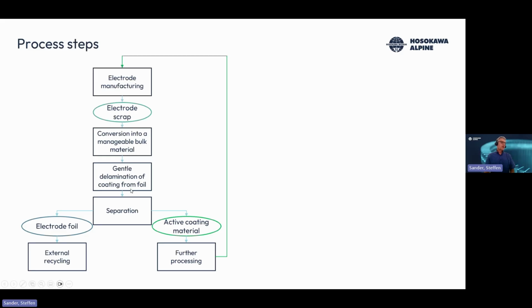So that's why you first of all have to convert this stream of scraps into a manageable bulk material. And then, of course, you need to gently delaminate the coating from the electrode foil. So these electrode foils are very thin metal foils. We think that mainly this would be applicable to cathode electrodes, since the value content is much higher here. But basically, that could also be used for anode materials. But you have to delaminate the coating from the foil, and then you need to separate the electrode foil.